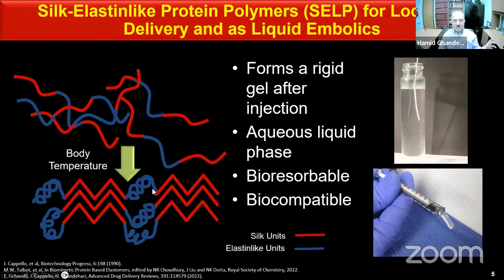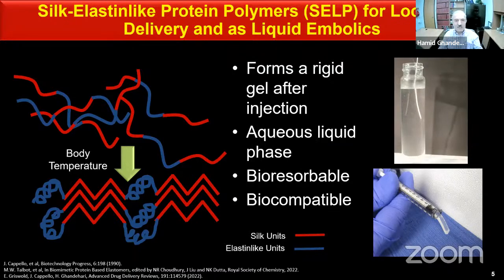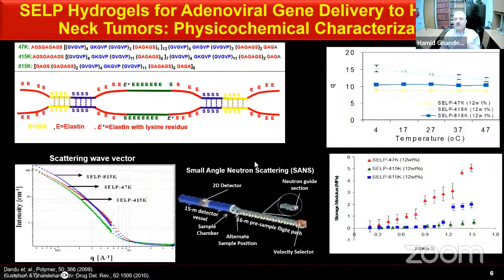depending on the number of silk and number of elastin that you have in the monomer sequence, but also importantly, depending not only on the number, but also the exact sequence of silk elastin that you have in these polymeric materials. So over the years, we have synthesized or biosynthesized, if you will, a number of these analogs. Several of them are shown here. In brackets, you can see the monomer sequence.